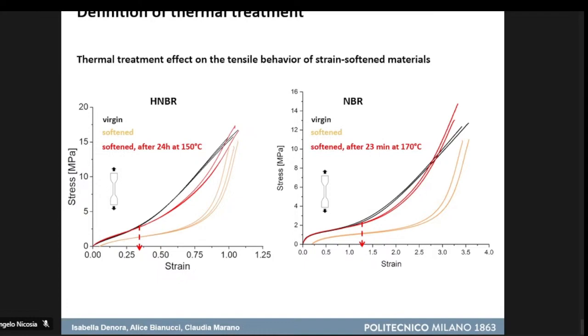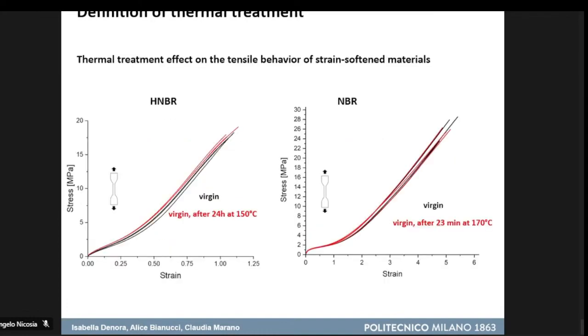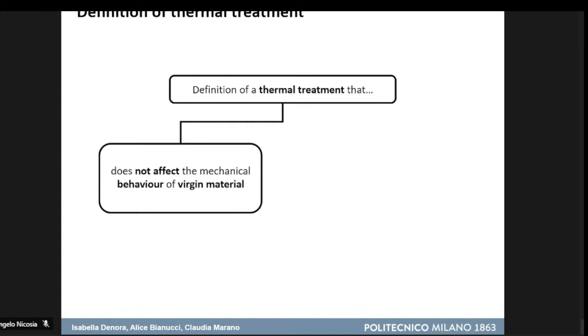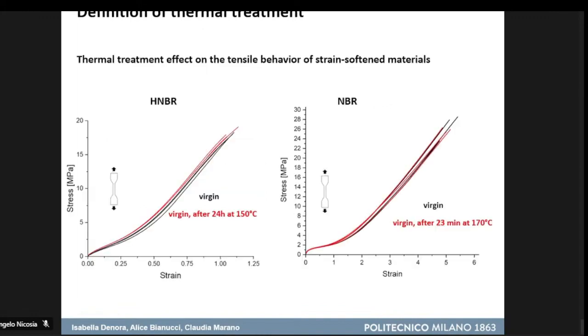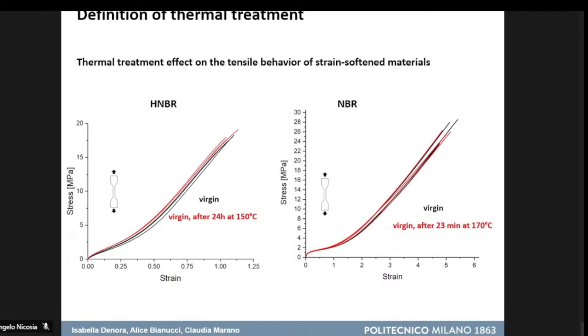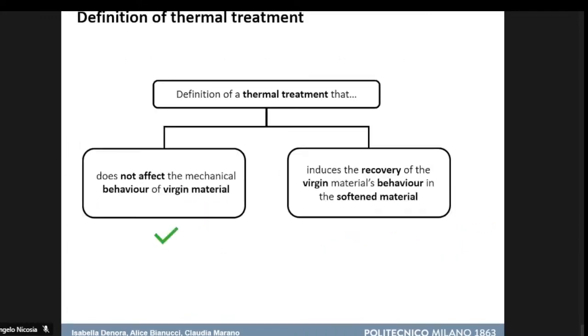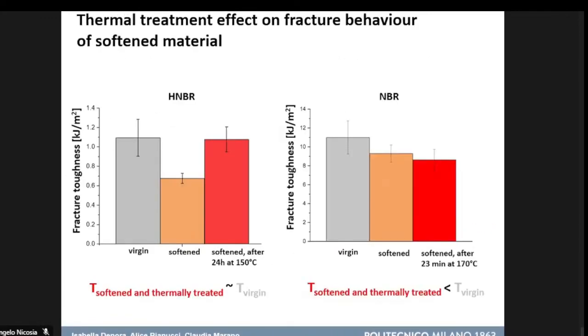And moreover, we have also controlled the effect of the thermal treatment on just the virgin material. So here I've reported the tensile curves of the virgin material and of the virgin after the thermal treatment. We can see that with this type of treatment, no further reticulation was observed in both materials. Okay. And here the final results.